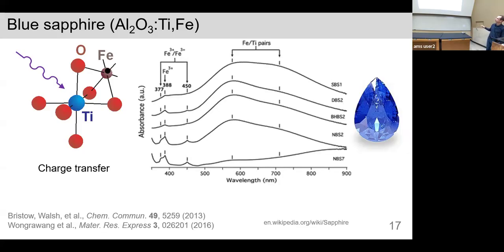And so it results in a broad absorption. This is showing from 400 to 900 nanometers of wavelength. People can see from 400 to 700. And this broad absorption is attributed to these pairs. And because that absorption is around 600 nanometers in the reddish orange and not much absorption in the blue is what you see.